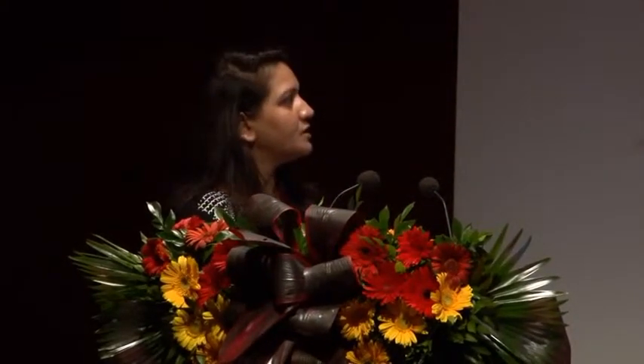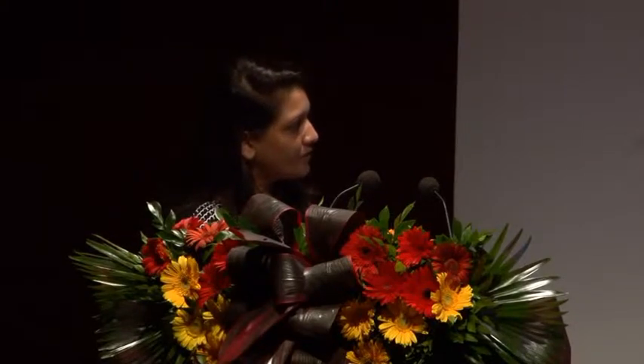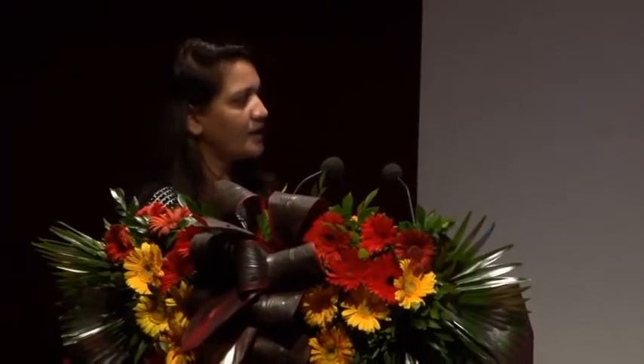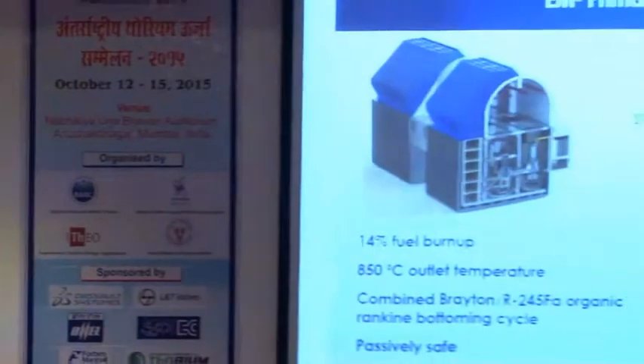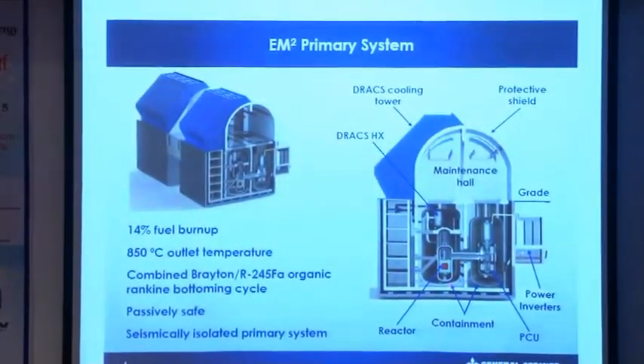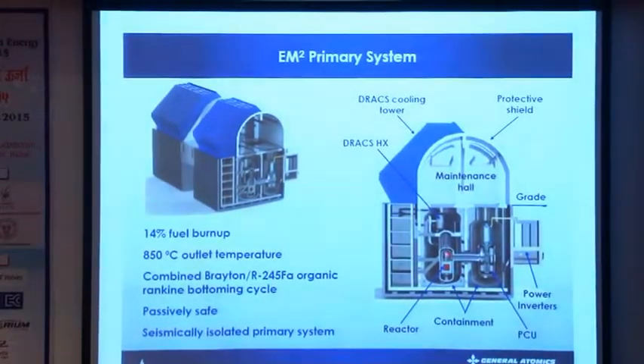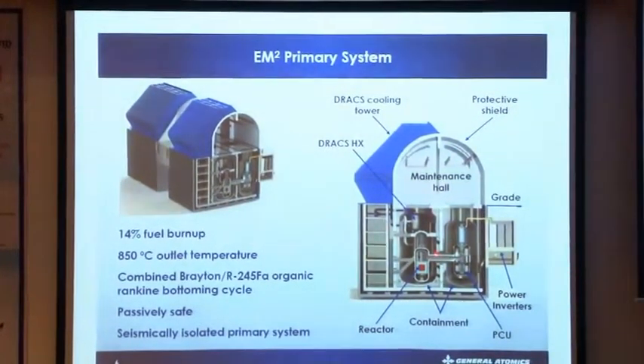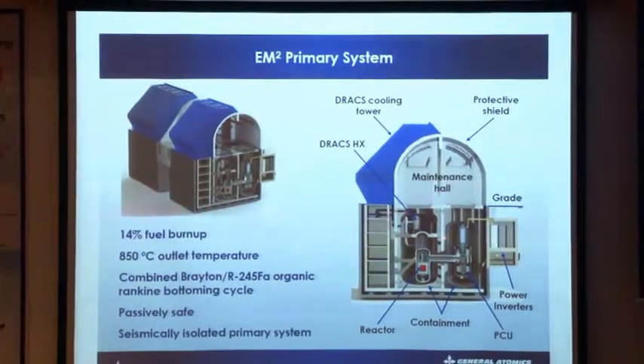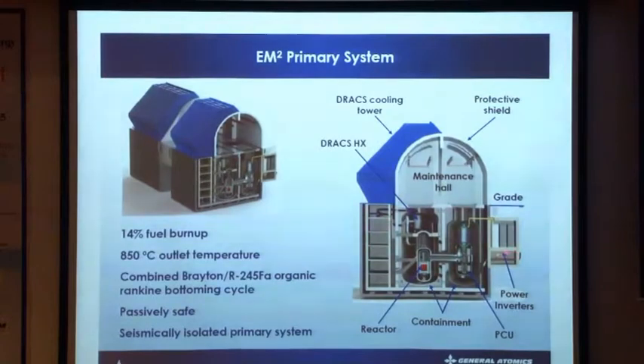So here's a closer picture of the primary system. You're looking at the reactor about here, which is fueled by uranium carbide fuel. It has a silicon carbide composite cladding material, and it's an upflow core where the helium goes from bottom to top. The reactor outlet temperature is about 850 degrees C, which drives this asynchronous high-speed compact turbine. And the higher speed of the turbine requires a power inverter to make it synchronous to the grid. And from here, the reject heat from the three coolers of this turbine goes to an organic Rankine cycle, and that extracts a little bit more energy out of the fluid, and thereby we are able to get 53% net efficiency. It's a passively safe system.